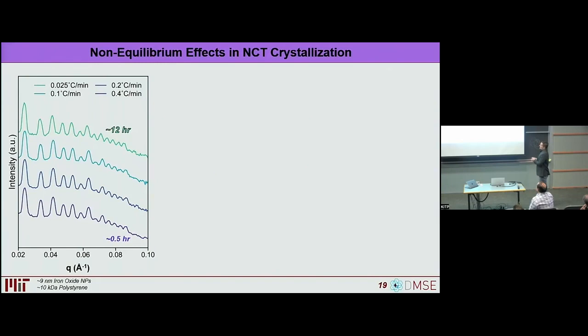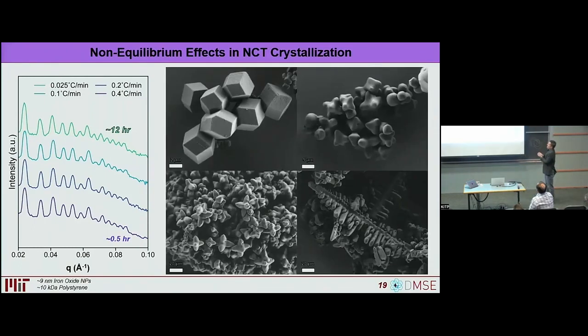So Matt took these particular particles, 9 nanometer iron oxide with about 10 kilodalton polystyrene. To give you a frame of reference, that's about a 10 nanometer thick shell of polymer. And he cooled them down at different cooling rates, from cooling over half an hour to 12 hours to even longer. And what we see is that there really isn't any change in the quality of the crystal regardless of the cooling rate. But what becomes more fascinating is what happens when you take a look at these under the microscope. So Matt took all of these samples down to the SEM and looked at them, came back to my office and said, Rob, I'm really confused. I don't know what's going on. Because sometimes I get these rhombic dodecahedra that I predict, and sometimes I get these things that look like hexapods, and some other times I even get things that look like these weird dendritic structures.